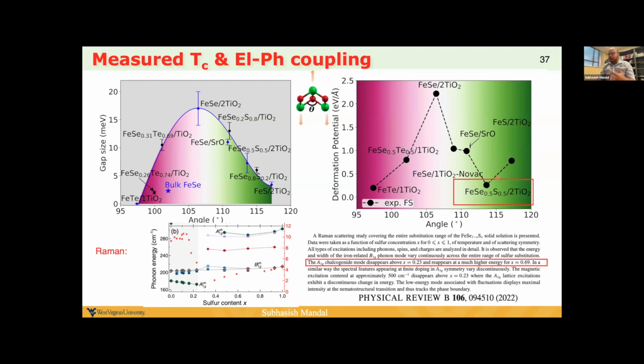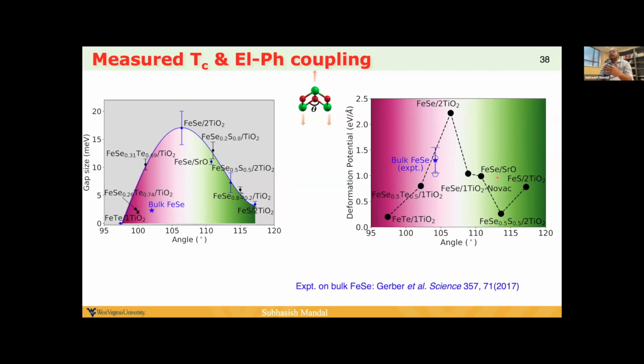So then we are seeing a similar trend to what we are seeing with the gap as a function of the angle, the single structure parameter. And then if we plot the one that was measured directly in the lab for the bulk with the angle, and here is the star, and the theory value with the maximum deformation potential and the average, it is perfectly aligned.